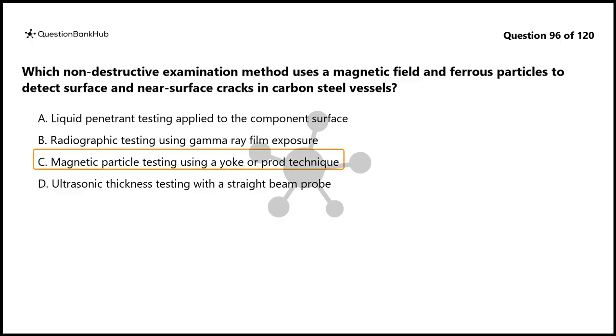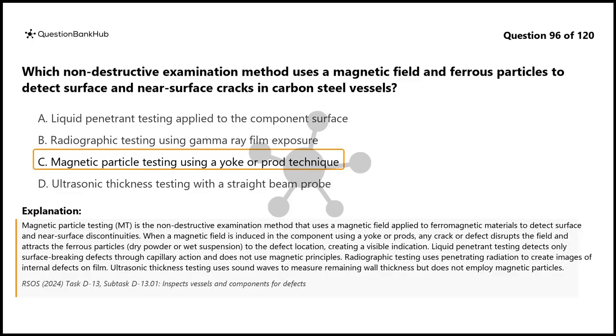The correct answer is C. Magnetic particle testing. Magnetic particle testing is the non-destructive examination method that uses a magnetic field applied to ferromagnetic materials to detect surface and near-surface discontinuities. When a magnetic field is induced in the component using a yoke or prods, any crack or defect disrupts the field and attracts the ferrous particles, dry powder or wet suspension, to the defect location, creating a visible indication.